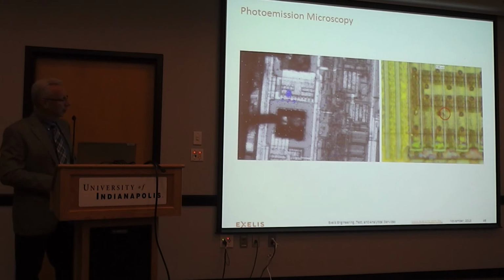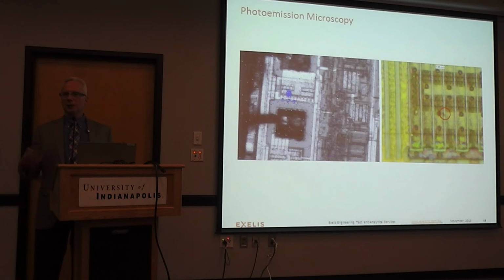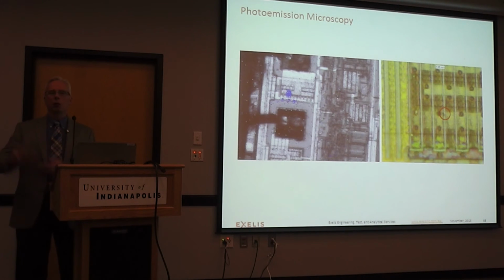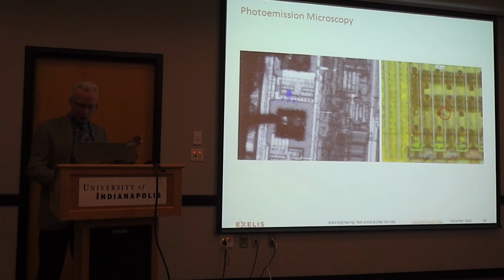Make a long story short, this corresponds with an electrical overstress damage site that we proved existed with this photo emission microscopy. Turned out to be a test set issue, wafer level test. The test set had multiple power supplies that had to power up in a certain sequence. If they didn't power up in the correct sequence, they could cause an electrical overstress, and that's what happened here.